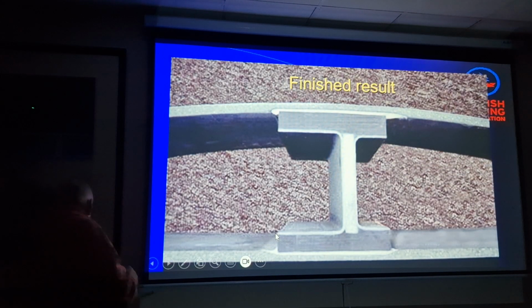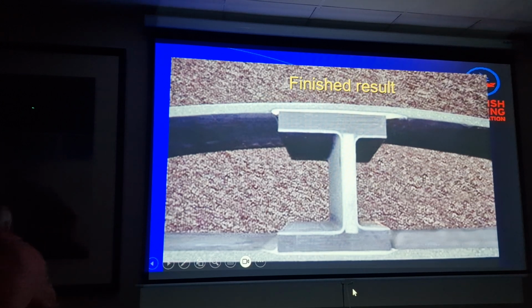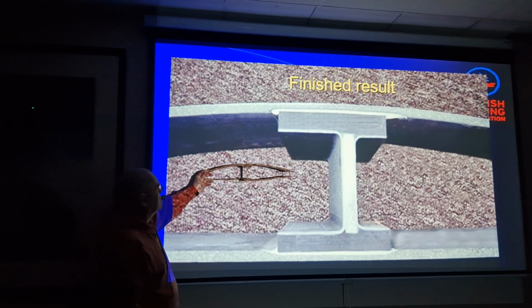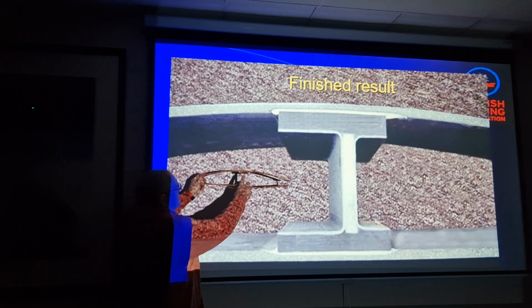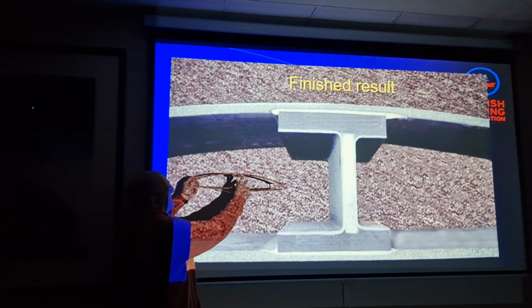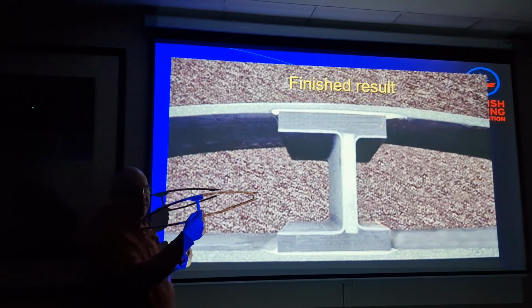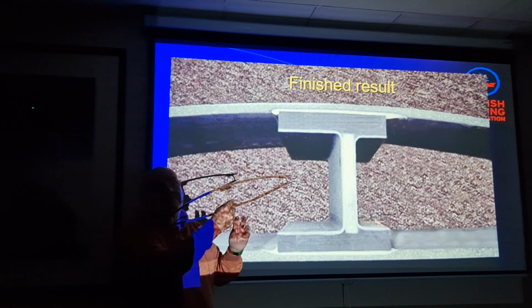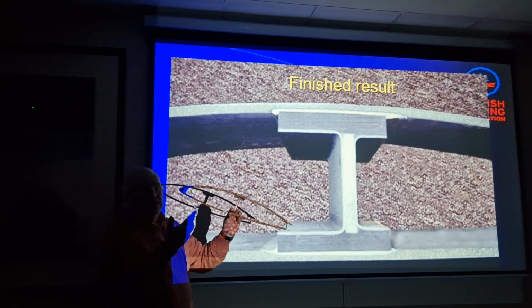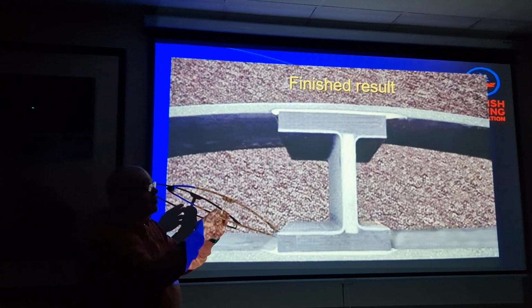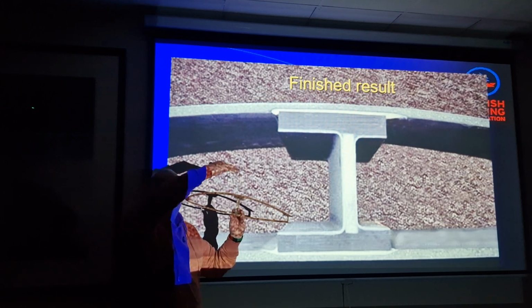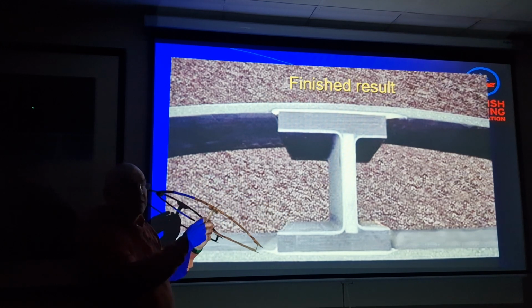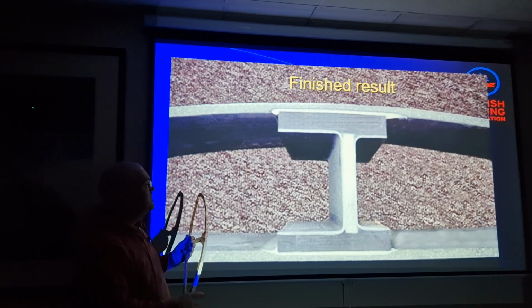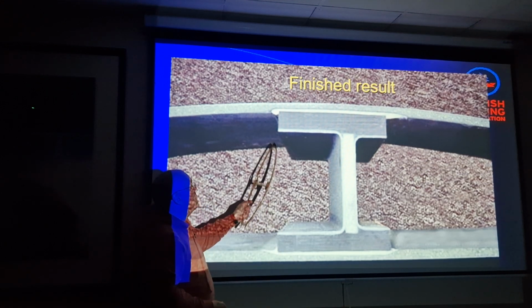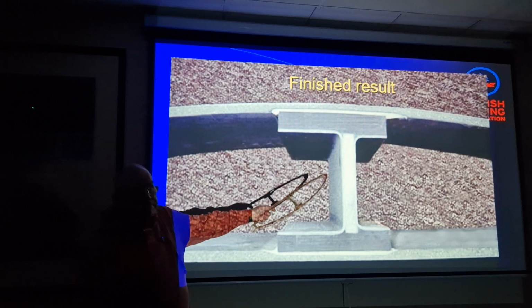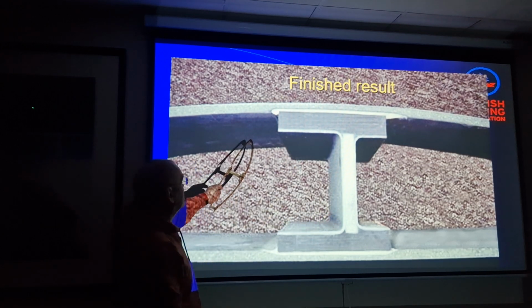Now, compared to this ASW20 wing, the build quality is better. Because you probably can't see it very well, there's a massive, about 3 or 4 millimeter line of resin here. Because in those days, these were handmade. This mold was made in 1976. And in those days, no CNC machining. It was all done by hand tools. So they always made spars and ribs smaller than the wing. And they filled up the gaps with resin to guarantee you could always squeeze it in there. It was always going to fit. With modern CNC machining, much higher quality. And so on. No excess resin.